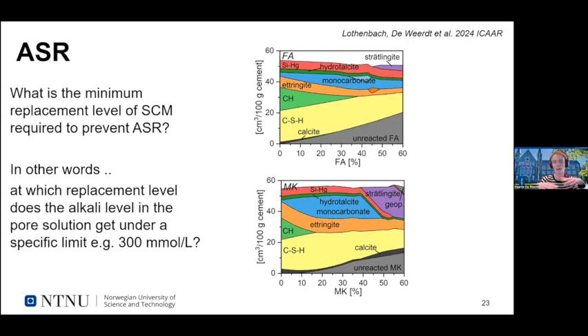We did some literature search, and this is a lower limit that counts for many aggregates, but know that this limit is dependent on how reactive the aggregate you're looking at is. But we took, for simplicity, 300 millimole per liter. And then we used SCMs to see how the replacement level of various SCMs affects the alkali concentration in the pore solution. Here I just took a few examples, but in the paper there are more. We did this for fly ash and metakaolin. And what we do is we look at the volume of the hydrates formed per 100 gram composite cement, and we vary the replacement level of the Portland cement with fly ash, going from 0 to 60 with fly ash and 0 to 60 with the metakaolin.